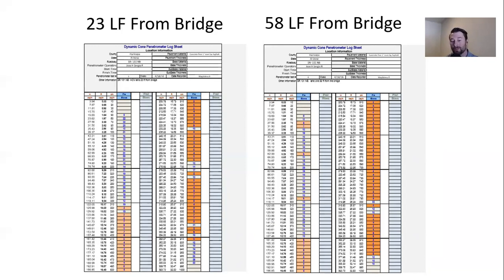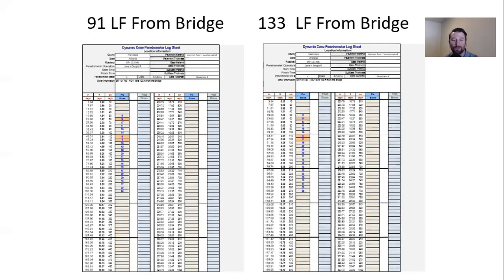And the more blows it takes for that rod to travel 10 centimeters, the more dense and likely the greater load bearing capacity that soil is going to have. If it travels a full 10 centimeters in one blow, that's very loose soil, or possibly a void. In some of these cases, I don't have them here, some of these single blow counts, that's not even really a full blow. That's the weight of the hammer. So it was just sliding 10 centimeters at a time into the embankment.